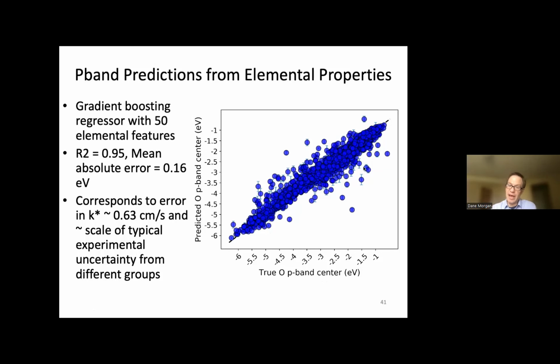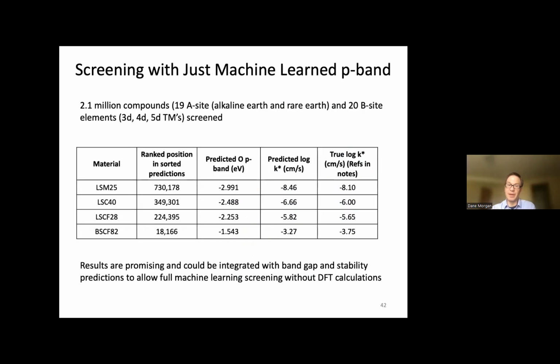And that this error, although it's significant, it's not nothing, corresponds to about half a log unit, or in K star. I should have said log K star here, about half a log unit in the surface exchange coefficient. Actually, that's about the error between any two experimental groups. So although we don't have a perfect prediction, experimental K star values aren't perfect either. So this actually isn't too big a deal. So now we can do something we couldn't do before. We can actually run through essentially every perovskite we can possibly think of and predict their p-bands, and then use that to predict their surface exchange coefficient.